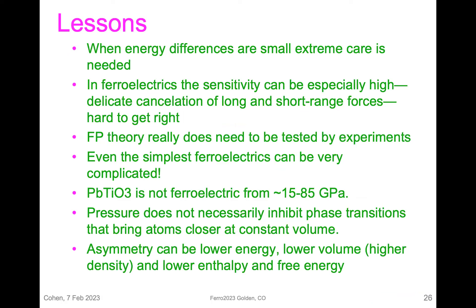Since the bands are basically the same, I think it just must mean that the O 2s states are more diffuse in the ferroelectric phase. To wrap up: one of the curses of ferroelectrics is also one of the good things — they're so sensitive to everything, and that's why we're here. But the energy scale is really, really small, so you have to worry about that. This goes back to the very delicate cancellation of long-range and short-range forces, and very small changes in how you treat things can change phase stability.